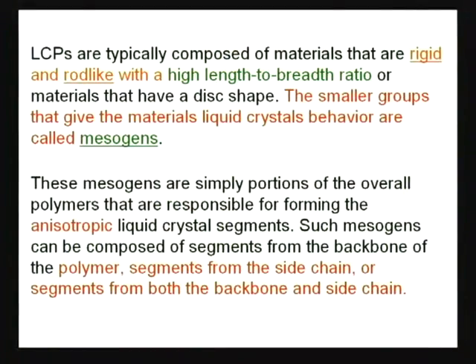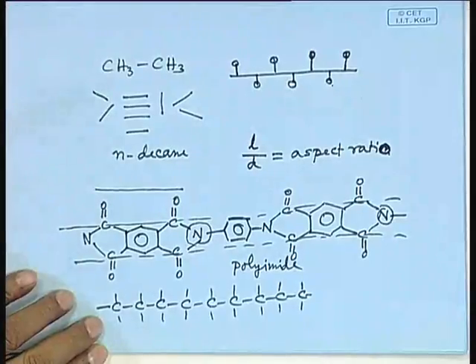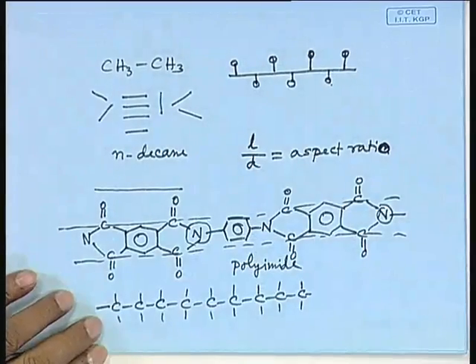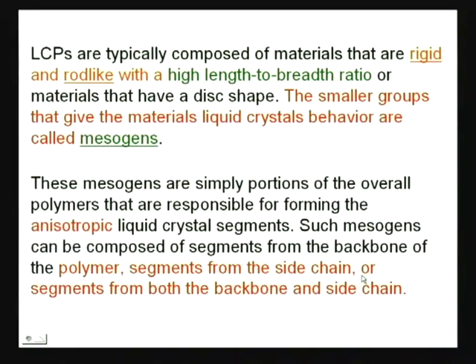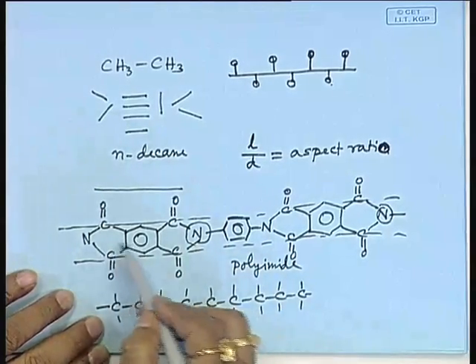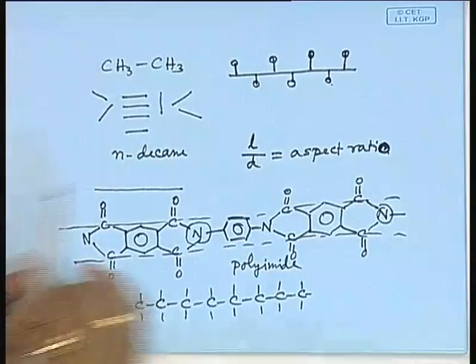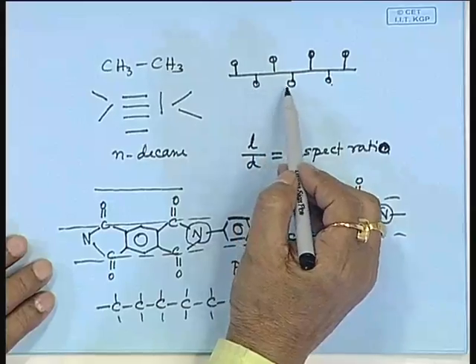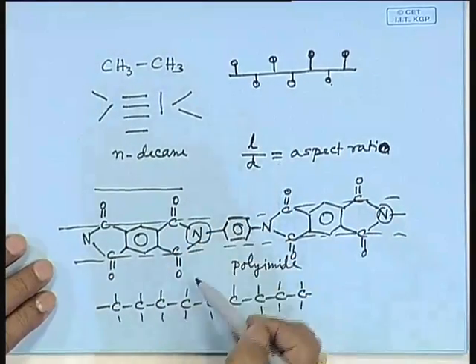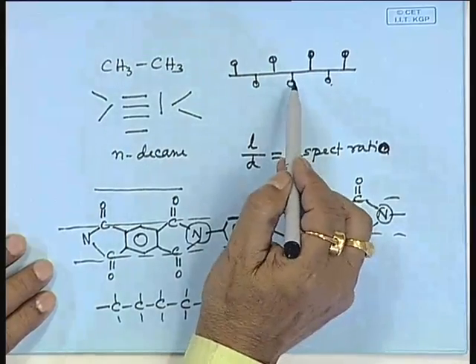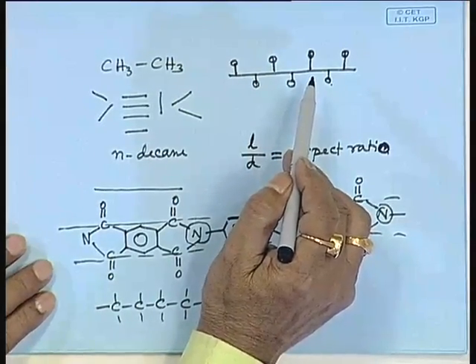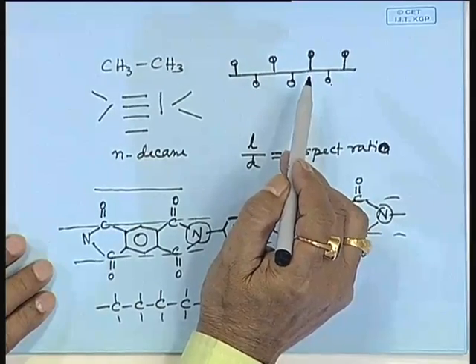These mesogens are simply portions of the overall polymers that are responsible for forming the anisotropic liquid crystal segments. Such mesogens can be composed of segments from the backbone of the polymer, as I told in this case, segments from the side chain, as I told in this case, all right, or segments from both the backbone and side chains. That means you can have a polymer where mesogens are placed along the backbone chain. You can have liquid crystalline polymers where mesogens are placed as pendant groups. You can have a polymer where both backbone mesogens as well as pendant mesogens contribute to this mesophasic structure, liquid crystalline behavior.